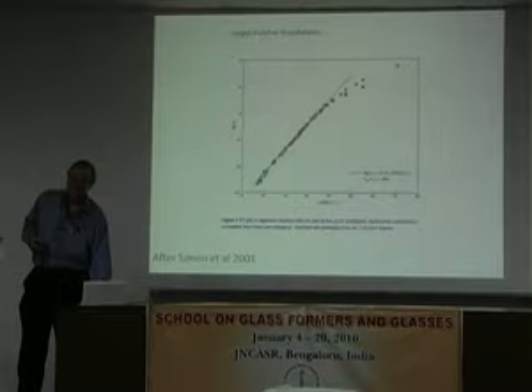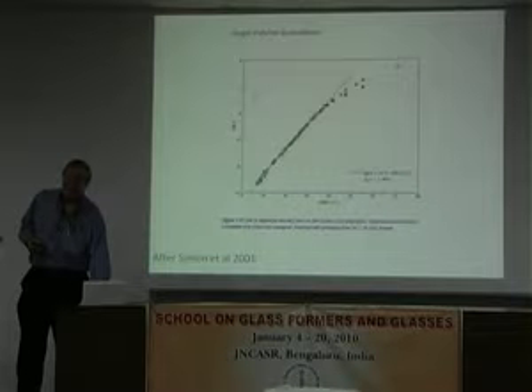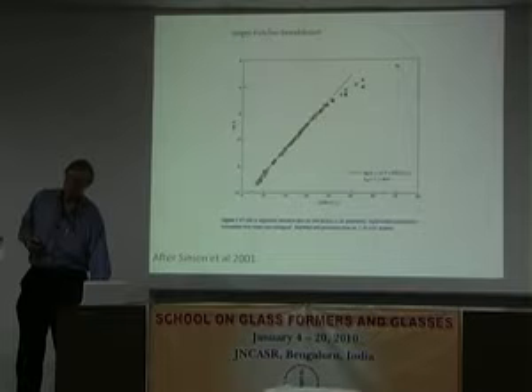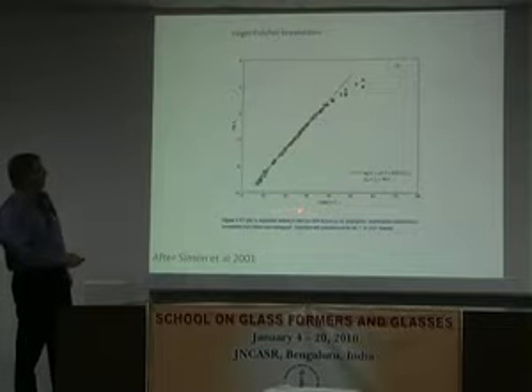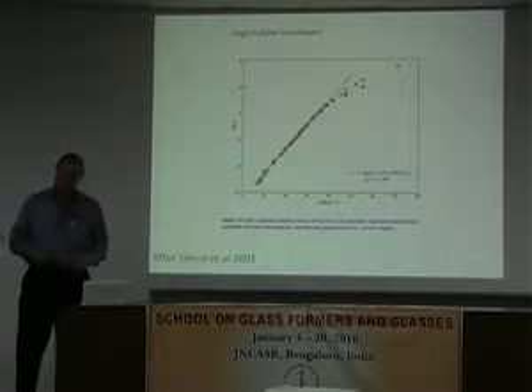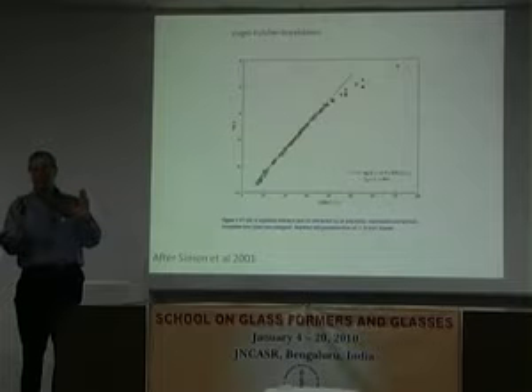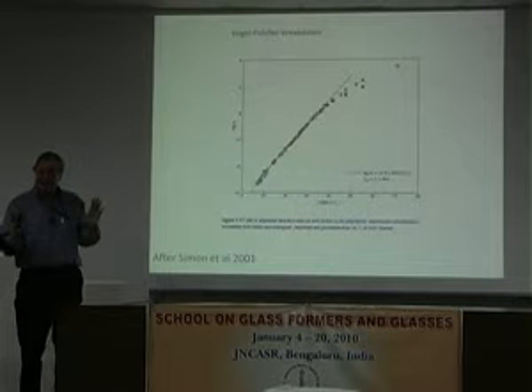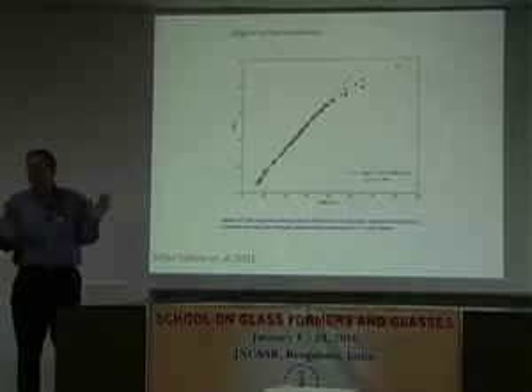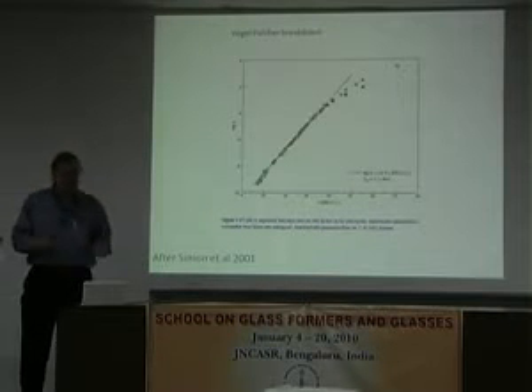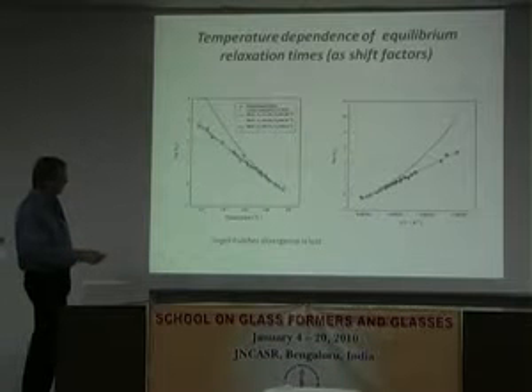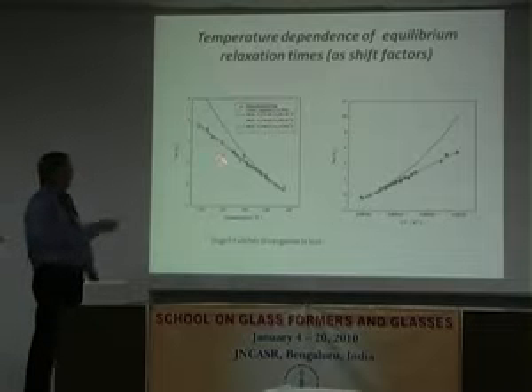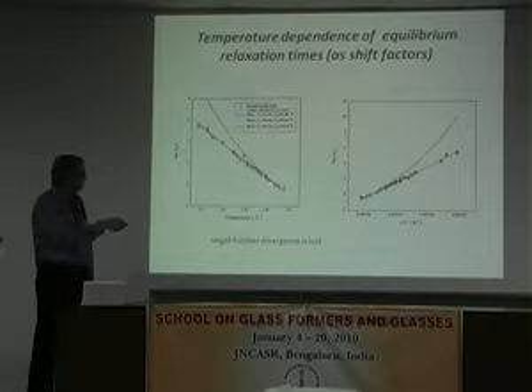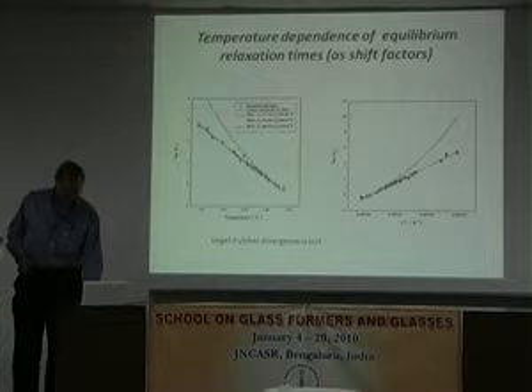Those fits still depend on what you choose as T infinity. So you take one part of the data, you say it fits Vogel-Fulcher with a certain T infinity, but if you take the experimental data beyond that, you find that doesn't work. Is that a fair statement? Well, yeah, obviously this depends on the T infinity that you choose, but if you want to have even close to a reasonable range of where you think things are fitting your data without making it too narrow, it's not that issue, right? But again, in this case it's only a 20-degree temperature range. I could probably fit a Vogel-Fulcher through that, right? But it does continue onwards, right? Yeah.